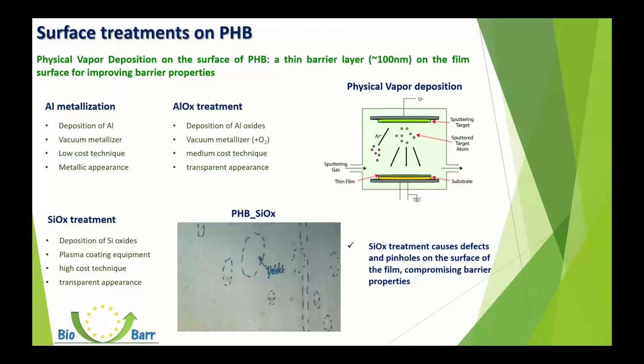AlOx treatment is also widely used in flexible packaging and consists in the deposition of a thin barrier layer of aluminum oxide, and is performed by using a vacuum metallizer, as for the conventional metallization, but introducing oxygen in order to oxidize the aluminum before the deposition on the substrate. This is a medium cost technique, as it requires the use of a protective layer, as the AlOx barrier layer is quite fragile, but this kind of treatment doesn't compromise the appearance of the polymer surface, as the thin barrier layer is transparent.